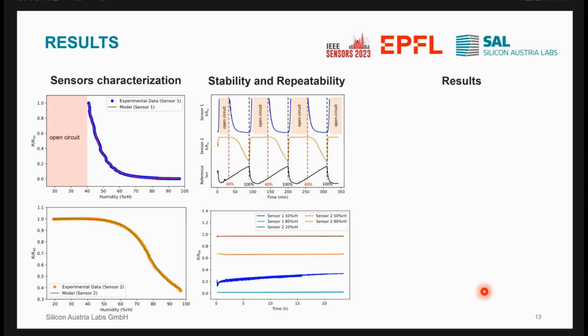Following this, both sensors have been characterized. Here on the upper left side, you see sensor 1, the one without the conductive bridge across the electrode structures. And as expected, below a certain ambient humidity level, the sensor resistance rises and can be considered an open circuit, as it couldn't be read out even using our laboratory equipment. Below this, you see the sensor curve of the sensor 2 design, where, as expected, the resistance is limited to a certain threshold, and it won't rise above this.